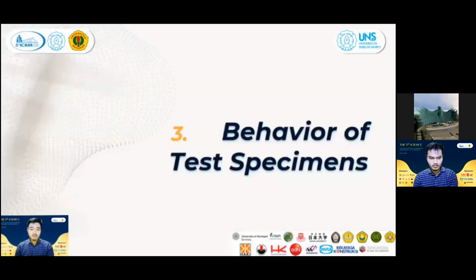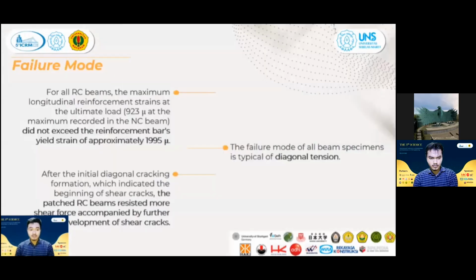Next, behavior of test specimen. The failure mode. For all RC beams, the maximum longitudinal reinforcement strains at ultimate load did not exceed the reinforcement bar yield strain. The failure mode of all beam specimens is typical of diagonal tension. After the initial diagonal cracking formation, which indicated the beginning of shear crack, the patch RC beams resist more shear force accompanied by further development of shear cracks.